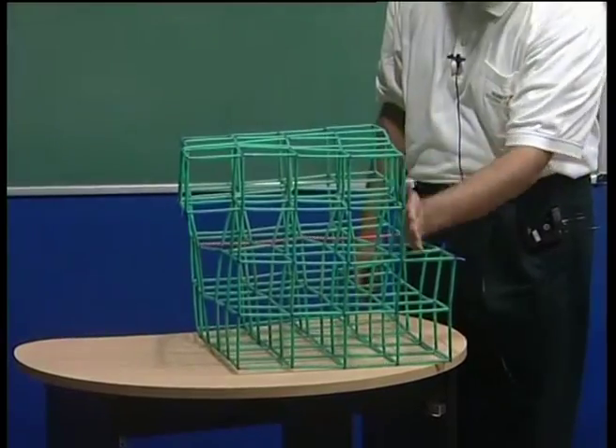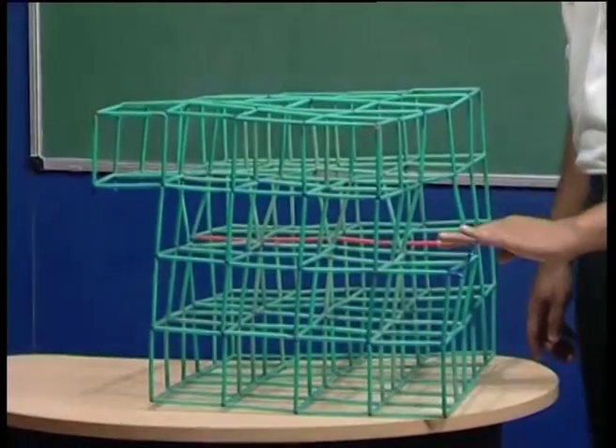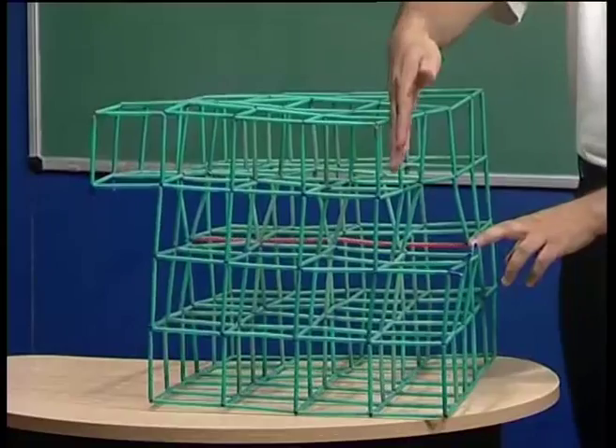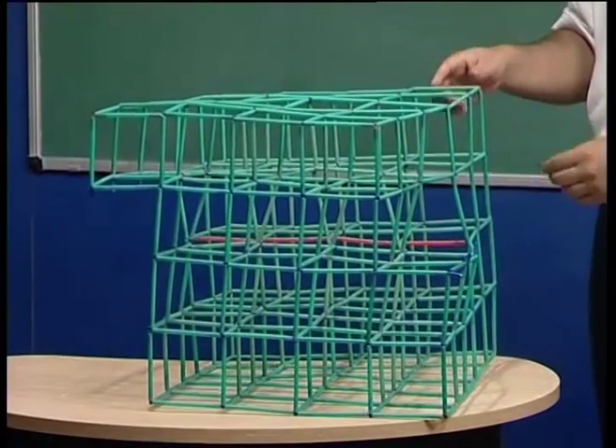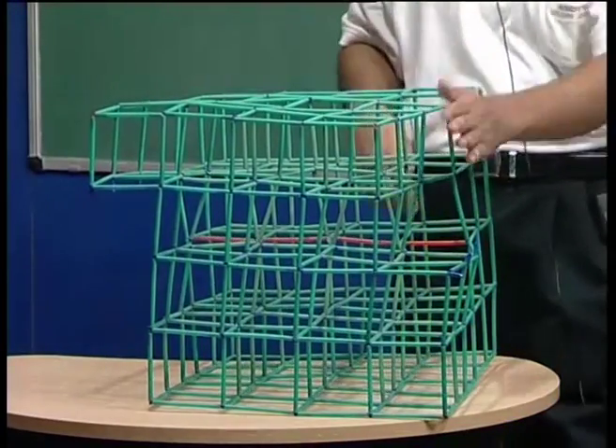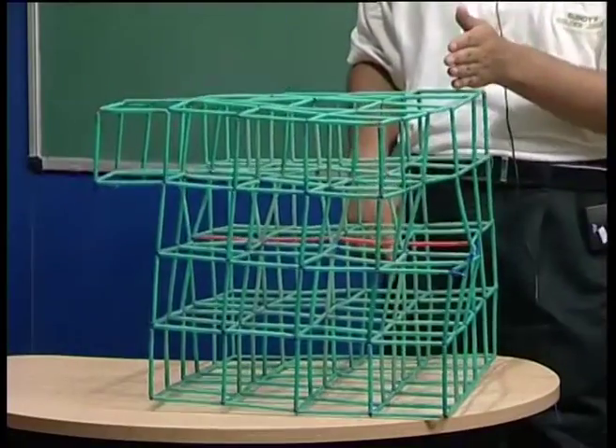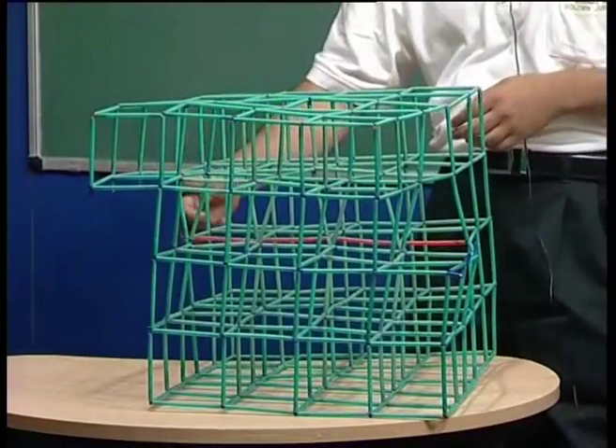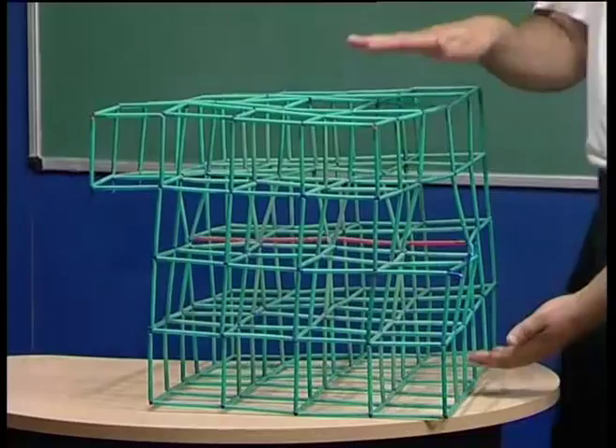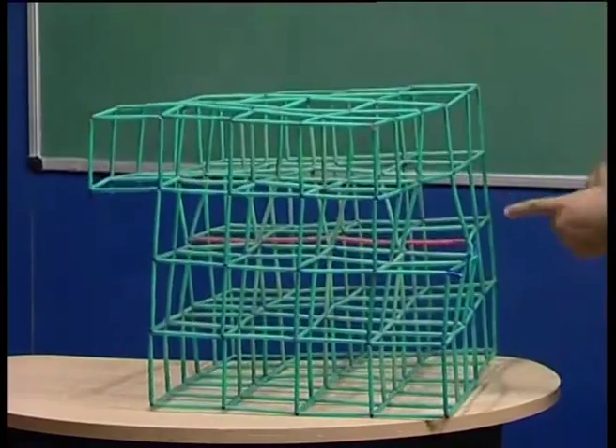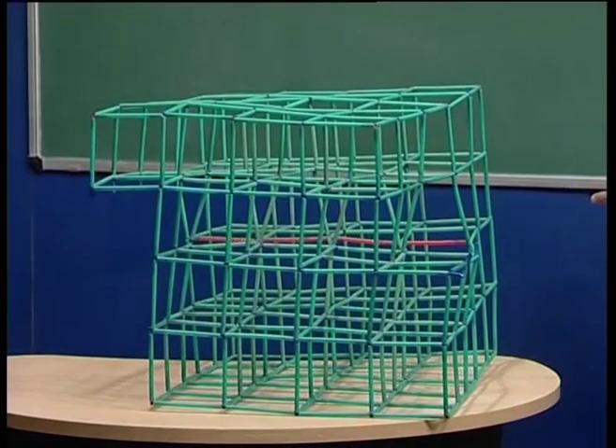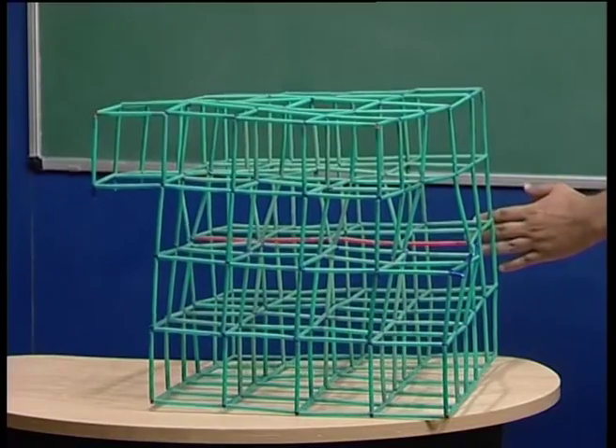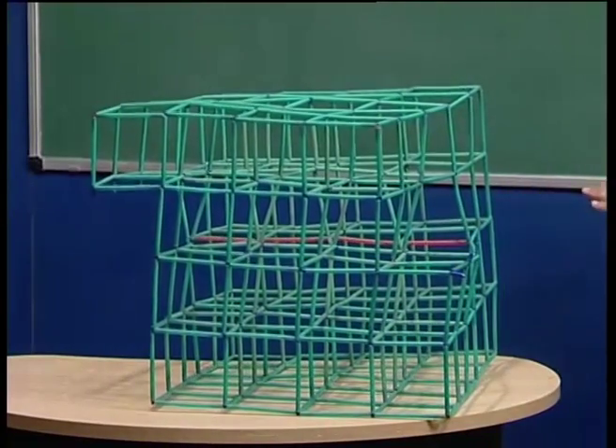This extra step you can see here has been created by this dislocation, and as this dislocation keeps moving, the step would propagate downward, and finally you will find that this whole crystal has a step here. That means even though I am shearing in this direction, the dislocation line would move in this direction, and finally it would leave the crystal from this back face and leave a complete step along the crystal.